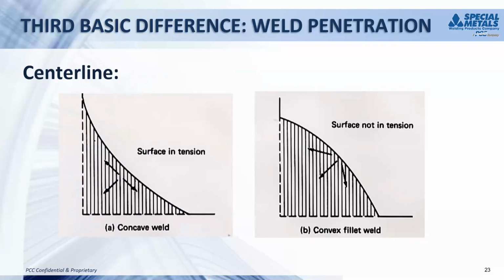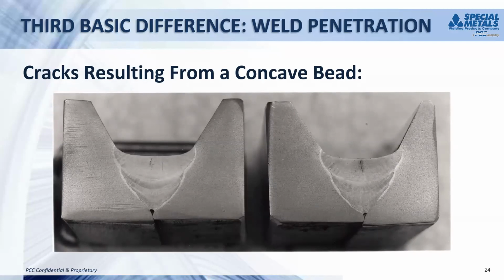The reason for this is that if you have a concave weld, you've got the surface in tension, and so the last to solidify, the centerline, is the one that's most easily pulled apart. If you have a convex surface, then it's not in tension, at least it doesn't have the full dose of tension, and so it's much more resistant to centerline cracking. Okay, John? Next. And these are just actual cracks that occur in a fully restrained joint. And typically this is what happens. You can expect this with nickel alloys. Next slide.